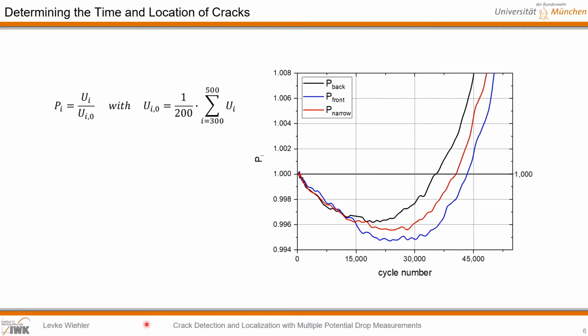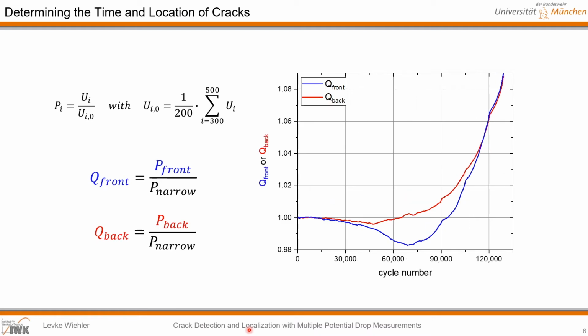To determine the time and location of crack initiation, the quotient Q is formed by dividing the individual potentials P front and P back by the relative potential of the narrow side P narrow, the potential in the center of the specimen's width. The run of the quotients is visualized in a graph to determine the point in time and location of the crack initiation. To be able to make a precise statement about the time and location of the crack initiation, the first 30,000 to 60,000 cycles are examined in detail.